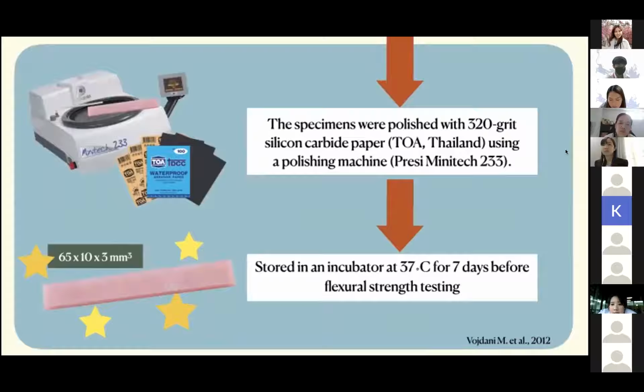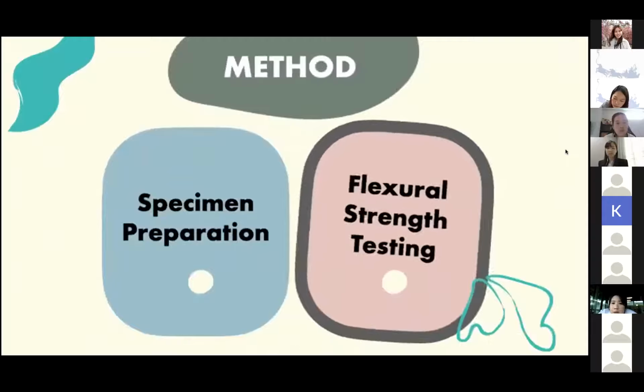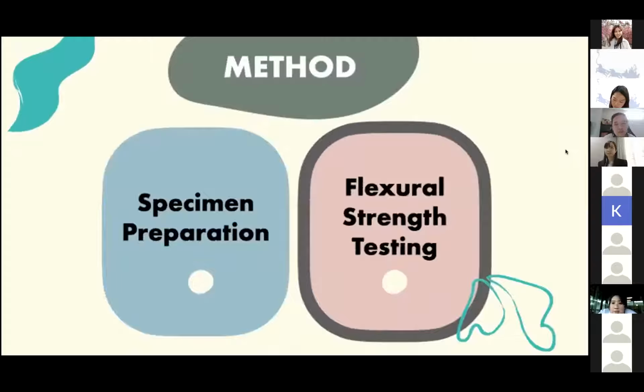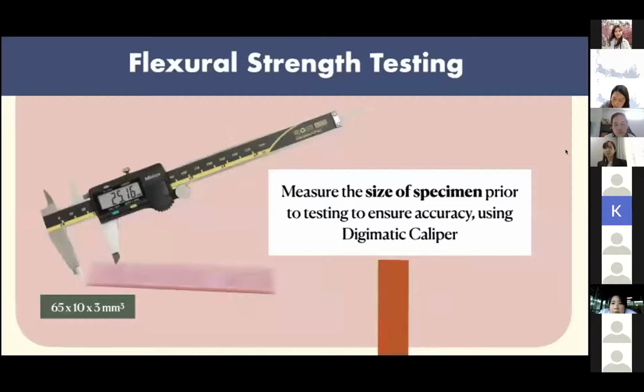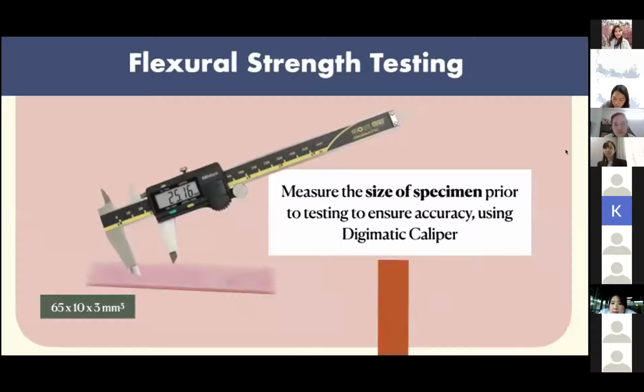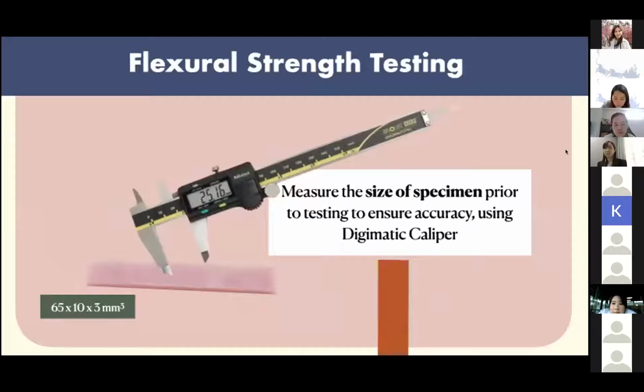Finally, the specimens were stored in an incubator at 37 degrees Celsius for 7 days before flexural strength testing. The final specimen size is 65 × 10 × 3 mm, according to ISO 1567. After all specimens were prepared, their flexural strengths were tested. Before testing, the thickness, width, and length of each specimen were measured using a digital caliper and put into the software.